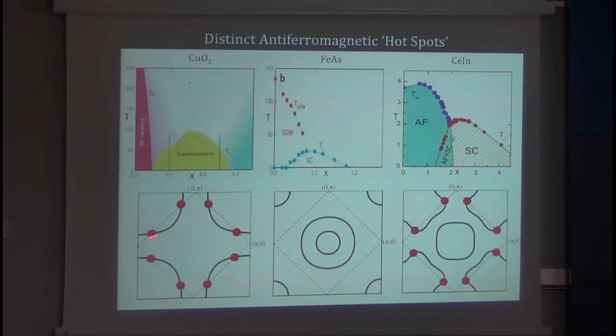Importantly, we have found that where the antiferromagnetic Brillouin zone, that's the Brillouin zone that would exist if the material was a stable antiferromagnet, touches the Fermi surface has a huge impact on which of the intertwined phases appear. The reason why there's no charge density wave in the pnictides is because the antiferromagnetic Brillouin zone does not touch the Fermi surface.